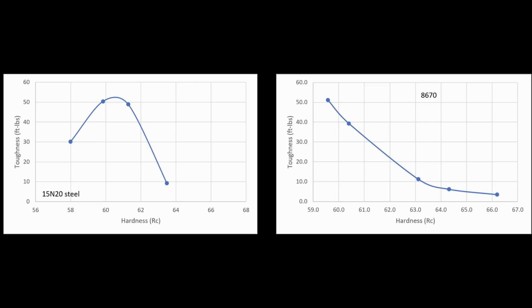However, as we saw with the tempering curves of 15N20 and 8670, when you tempered below 350 degrees, the toughness falls off a cliff. Now, the steel isn't suddenly super chippy or breaking really easily, but it looks more similar to other steels. It's not these chart-topping toughness steels anymore.